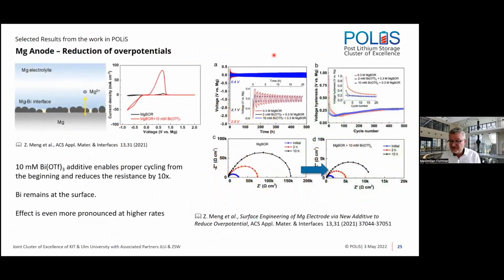Okay, next point is overpotentials, and as we all know, these multivalent anodes tend to passivate. If there's the slightest amount of water in your electrolyte, your anode stays passive and doesn't want to start working. What also came out from various sites recently was that alloys may work much better in that respect, that there's less build-up of blocking layers, and the kinetic barriers are much lower than with the pure metals.